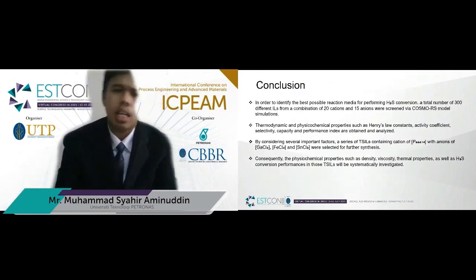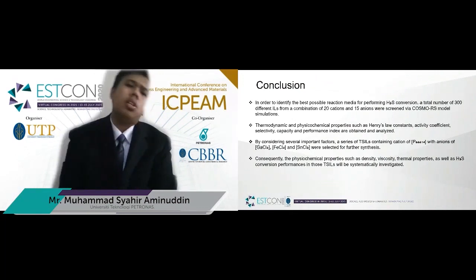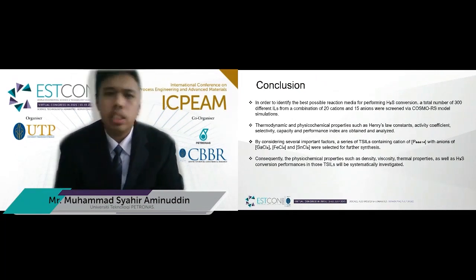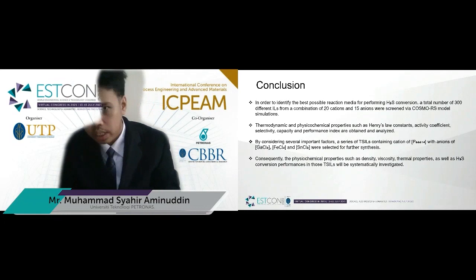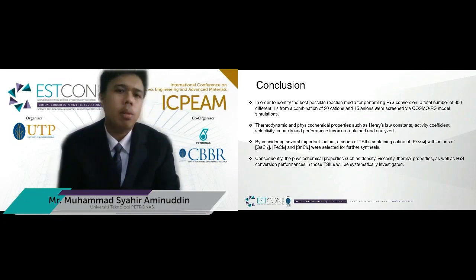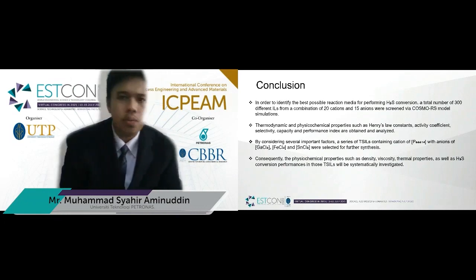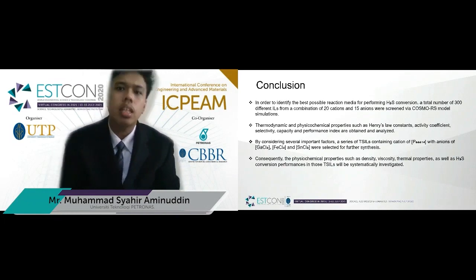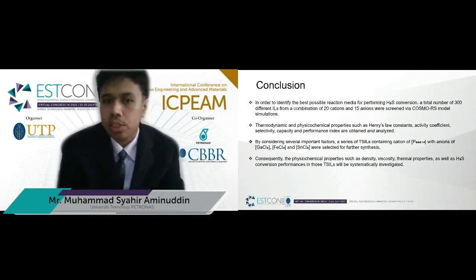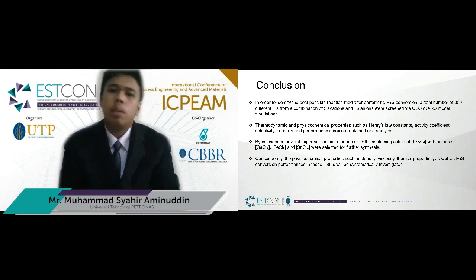Last but not least, I would like to conclude my presentation with this. In order to identify the best possible reaction media for the H2S conversion, a total number of 300 ILs from a combination of 20 cations and 15 metal chloride anions was screened by a COSMO-RS model simulation. The thermodynamic and physicochemical properties are also obtained and analyzed.